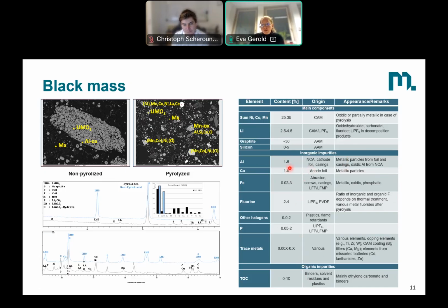The aluminium and copper residues are coming from the current collector foil. Then we have some iron impurities. We have quite a lot of fluorine in there, actually originating from the conductive salt or from the binder material PVDF. We have also halogens in there, so other halogens than fluorine. We have phosphorus in there, originating from the conducting salt once again, or from missorted LFP batteries. And there's a bunch of trace metals like titanium, zirconium, also calcium and magnesium from fillers, and also cadmium and zinc from missorted batteries. So you can see quite a bunch of different materials.